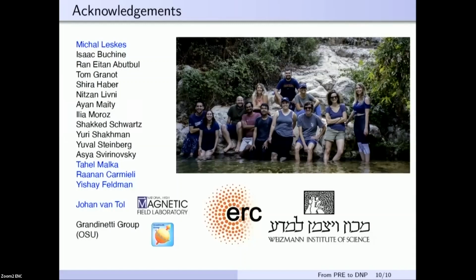Yeah, so thanks. I'm aware of your work, and we're actually also working on looking at exactly this question, why we have much better enhancement in crystalline materials over amorphous materials. So what we did is we prepared samples of analog composition, some silicate glass and silicate crystals, and just looked at the DNP enhancement, and we saw an order of magnitude difference, from 10 to 100, something like that. We've been scratching our heads, like why is this? And the conclusion that we get to is that it's a couple of different things contributing.